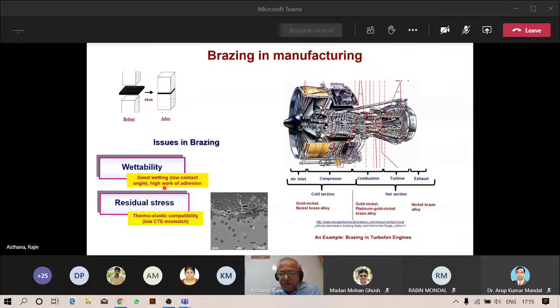When you have metal to metal bonding, especially in a system like a turbofan engine, these challenges are less critical because you're using metallic brazes to join metallic components. You're joining nickel-based superalloys or titanium or steel components in the lower temperature side. So the expansion properties are not very different, and also the wetting is quite good. That is not the case when you have ceramic to metal bonding. So that poses some additional challenges. Mostly in this talk, I'm going to look at the wettability problem, but let us first look at the thermoelastic compatibility issues.